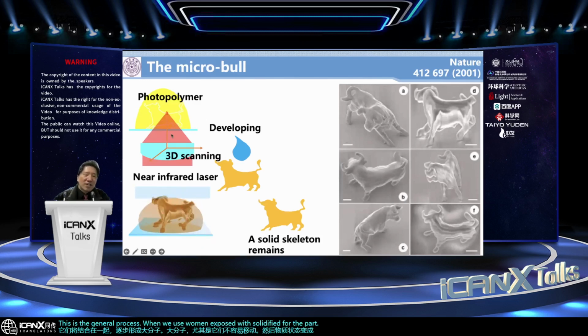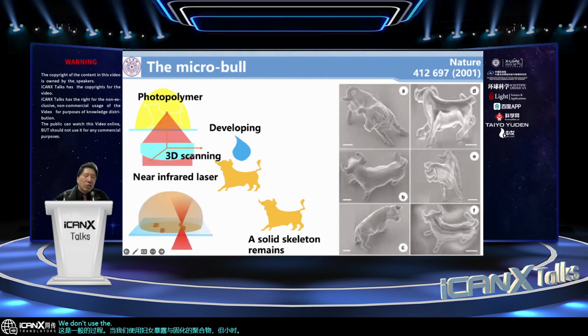But in our case, we don't use the UV irradiation. We don't use the visible, but we use the near-infrared laser. Then we can focus the laser into the material without power loss. And then we can control the light intensity at the focus spot so that at the focus spot the material can be solidified by the multiphoton absorption. Then if we do the 3-dimensional scanning, following the scanning locus, the material will be solidified into such a shape, almost any CAD designed shape.